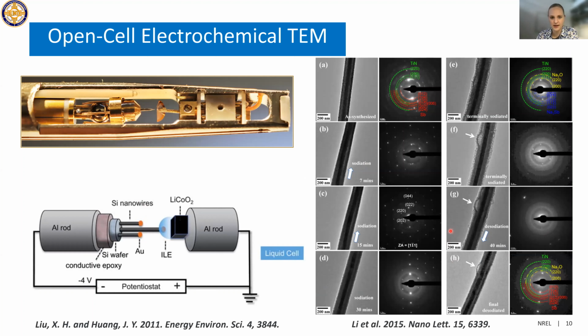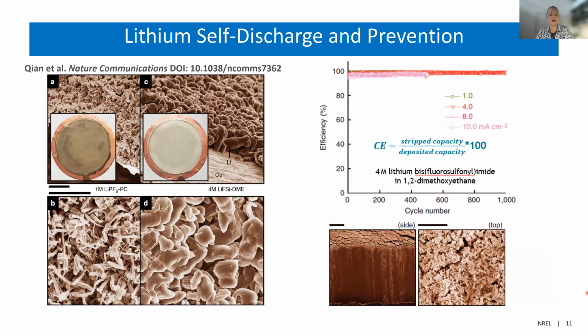And this is actually looking at a film on top of a nanowire during sodiation and desodiation, and seeing a buckling of that film due to the volume expansion in that material. And so I just want to show that there are other ways other than liquid cell imaging to look at these structures. Okay, so our group, we got very excited when we heard the results from PNNL on this new electrolyte, because they were showing a very different lithium morphology than what was known in carbonate electrolytes.